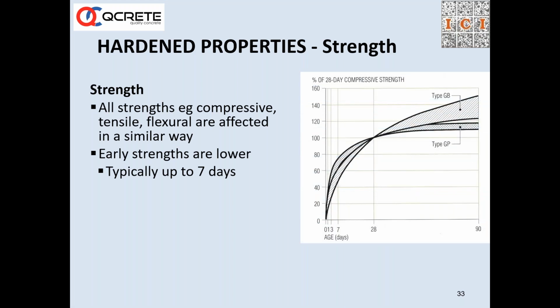And this is one of the favorites that we always talk about, the strength. So OPC is a dead horse after 28 days, means it will not gain much strength after 28 days. But when you are blending OPC with GGBS or fly ash, the curve goes up actually, and this is a significant contribution in terms of higher strengths at later ages. So the OPC cannot match with these supplementary cementitious blended concretes.